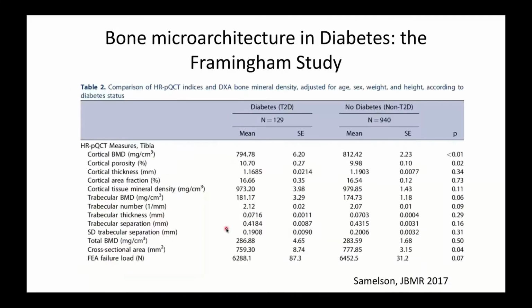And finally, the more recent and larger study from the Framingham group, Samelson, first author, and Bouxsein, last author. Now we have to deal with a larger number of diabetics than before, 129, and a very large control group. And here you have a little more significant differences, and they found an increase in cortical porosity that was significant. But again, the difference in porosity is about 1%. It's not a huge difference in porosity.